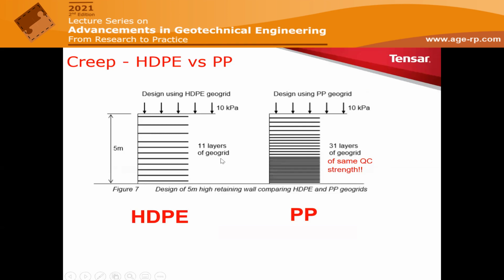of a certain QC strength. But if we opt to design with polypropylene geogrid, because you use the creep strength and not the QC strength, for the same performance, 120 years design life, we would need 31 layers of geogrid. And this is just massive because HDPE has very good creep characteristics, but polypropylene doesn't. And this is exactly why we use high density polyethylene and not polypropylene, even though polypropylene is much, much cheaper.